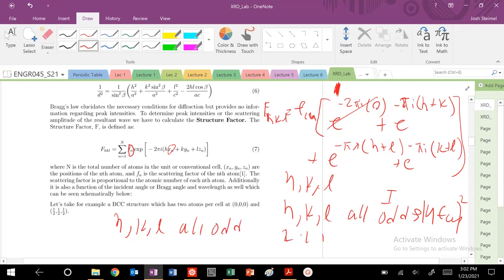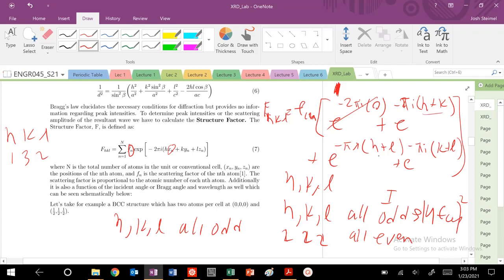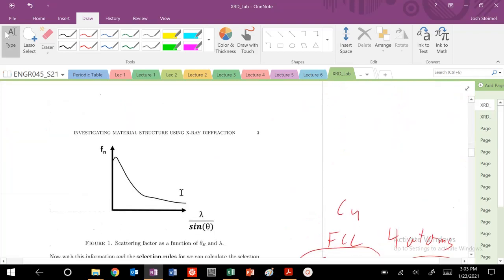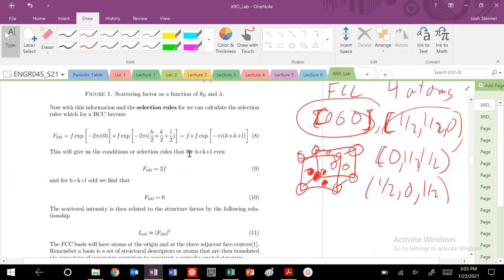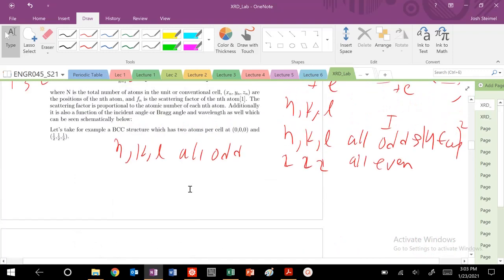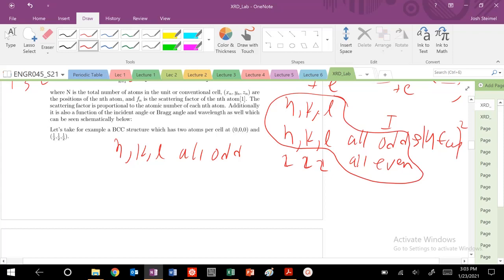What happens if they are all even, for example, 2, 2, 2? If they're all 2, 2, 2, I also see a signal. So that's good. All odd or all even. So that will work. So what if they are mixed? Let's say I have my H, K, L is 1, 3, and 2. Let's see how this happens. H plus K here, that would be even. So that works. H plus L, that would be odd. That's no good. And then K plus L, that would also be odd. So that's no good at all. So we see here that our condition, different from BCC, we need to have H, K, and L all odd or all even, and we'll see a signal. If they're mixed, no signal.